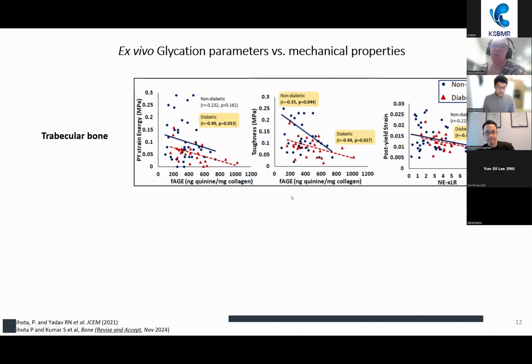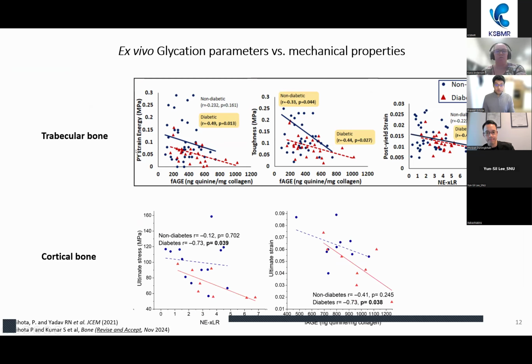And then we found a causal relationship between glycation parameter and mechanical property. So when the mechanical properties are plotted against glycation content, we found a negative association of mechanical property with glycation content. So with increased glycation content, the mechanical properties, mainly the post-yield properties, so post-yield strain energy, toughness, and post-yield strain, are lower or reducing for both trabecular and cortical bone. For trabecular bone, post-yield energy, toughness, and post-yield strain are decreasing with increasing glycation content, and in cortical bone, with increasing non-enzymatic cross-link ratio and FAGE content, ultimate stress and ultimate strain are reducing respectively.